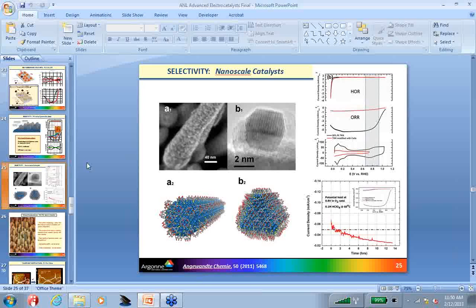So we performed several MEA studies on our catalyst of choice, which is multi-layered platinum nickel, and we were able to repeat the exact same performance in terms of specific area loss, which was only around 10%. However, specific activity was not as high as in our RDE measurements. It is important to emphasize that those measurements were not optimized, and we had to rely only on small amounts of catalyst, considering the limitations in our own lab, where we cannot produce huge amounts of catalyst.